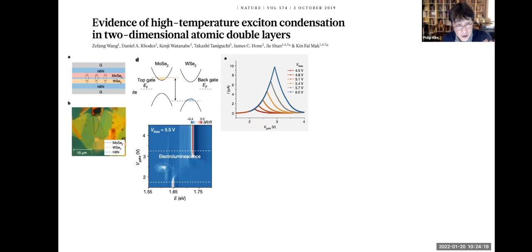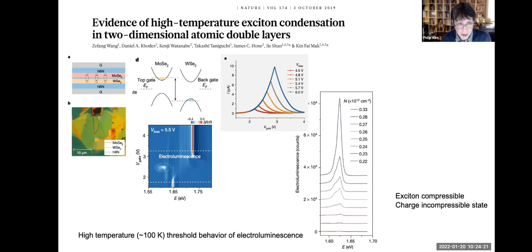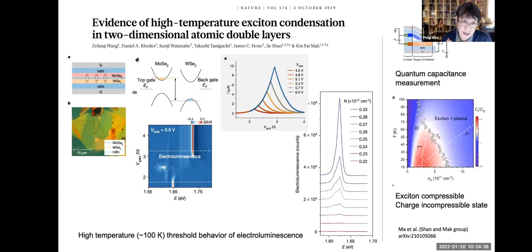It is coming through the so-called intralayer trion, but nevertheless, just observing this light emission from this device, as well as carefully measured capacitance, they show a strong indication that there is indeed interlayer exciton coupling happening, and they may actually condense into a macroscopic quantum state. And this condensation temperature is not necessarily extremely low, it's something like tens of Kelvin or 100 Kelvin, right? Indicating that indeed this can be a way to create robust excitonic states out of the system.